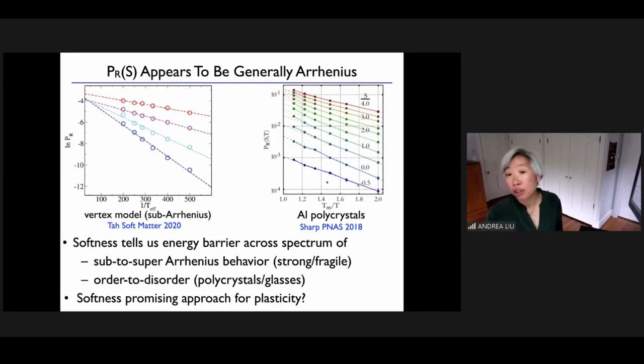And here we actually applied it to a crystalline system. This is aluminum polycrystals. So with grain boundaries, it turns out that the soft particles are in grain boundaries, right? Particles of very low softness are in crystal regions, as you would expect. And again, even in this system, the probability of rearranging is Arrhenius, so we're getting the energy barriers, and these energy barriers are of the magnitude that you would have measured for aluminum. So softness tells us this energy barrier across the whole spectrum of possible behaviors, from strong to fragile to even sub-Arrhenius, and across the whole range from order to disorder.